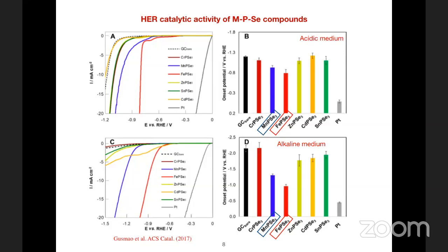The next one is the similar experiments with the selenide compounds, and as you see, platinum has the lowest onset potential, followed by MnPSe3, FePSe3. So these are what was demonstrated in the experiments, and these are good news because one is looking to replace an expensive and rare metal like platinum to have efficient catalysts.